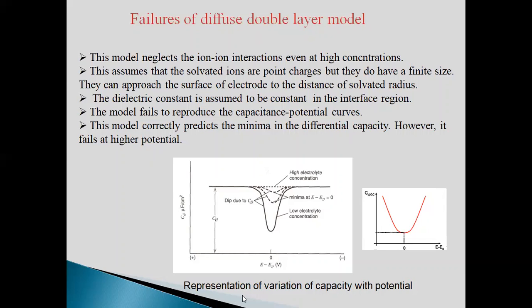As shown here, this model successfully explains the electrocapillary curve at low values of potential, as can be seen, but it fails to explain the capacity variation at higher values of potential. This is due to the capacitance catastrophe that occurs by assuming that ions are point charges. If the ions are point charges, then they can approach the surface of the electrode without any restriction of distance, and so this causes the increase in capacitance without any limit.